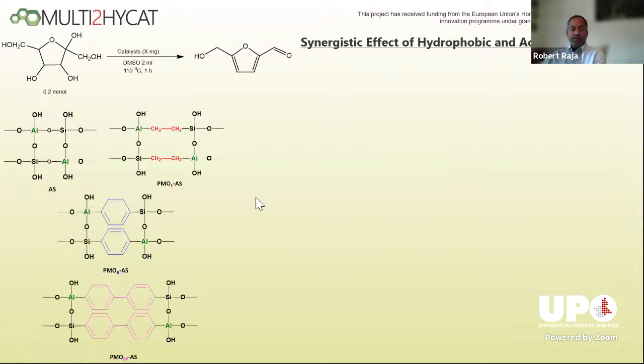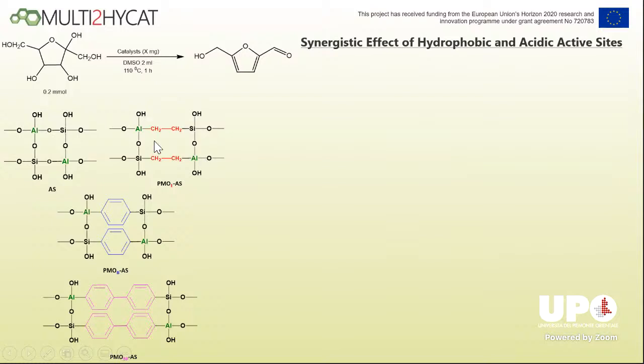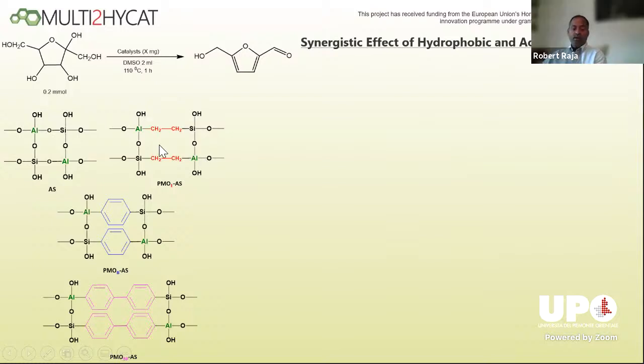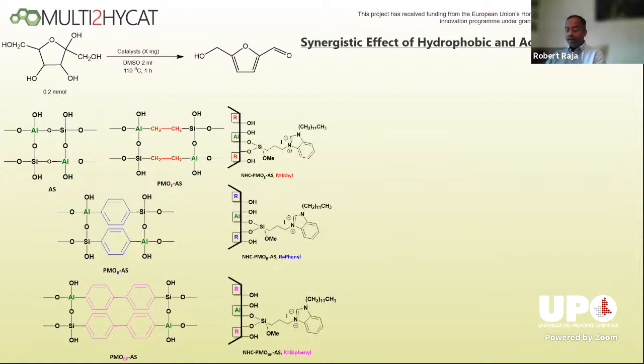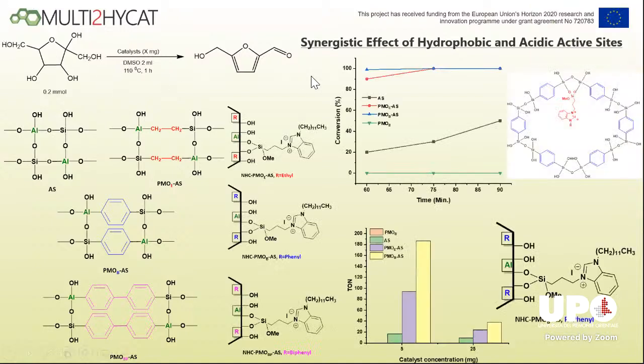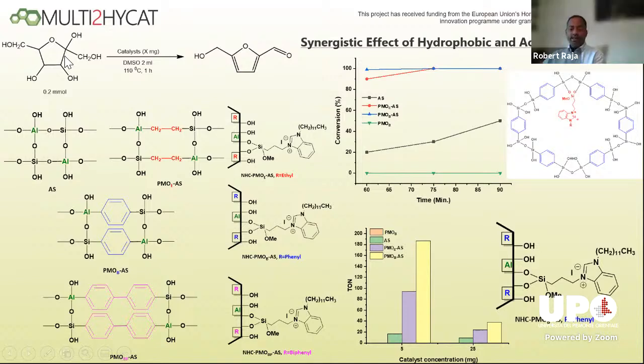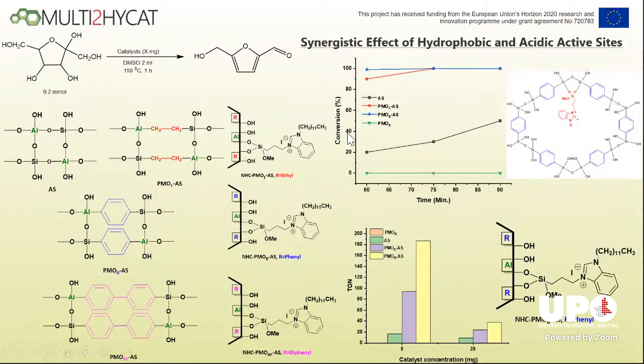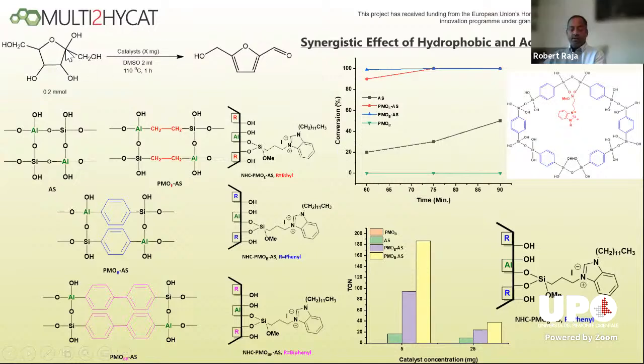So compared to the previous set of materials, with these materials, we now introduce an aluminium functionality. So we make periodically ordered mesoporous aluminosilicates, for example, as opposed to the purely periodically ordered organosilicas. And then we have looked at this particular target reaction, which is the dehydration of fructose. Now, what we see here is when you have purely just the hydrophobic entities, this is the periodically ordered mesoporous structure having the phenyl groups, which impart the hydrophobicity, which I showed you on the previous slide. Now, this catalyst is completely inactive when you look at the dehydration of fructose.